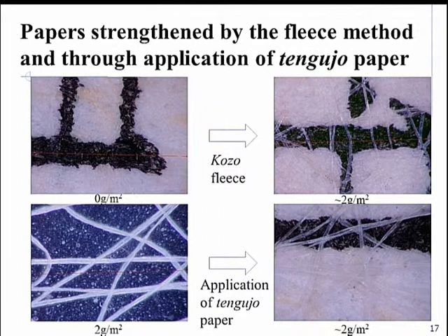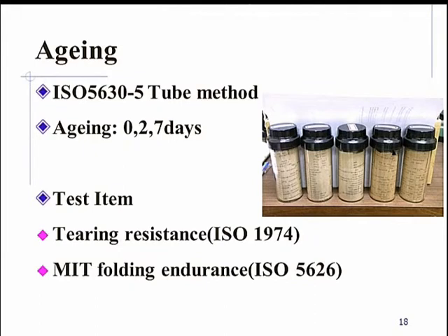Paper strengthened using the fleece method, 2 grams, and paper strengthened using a sheet of Tengujo, 2 grams, both appeared similar under the microscope. Physical measurements are taken before and after artificial aging to evaluate the efficiency of each treatment.